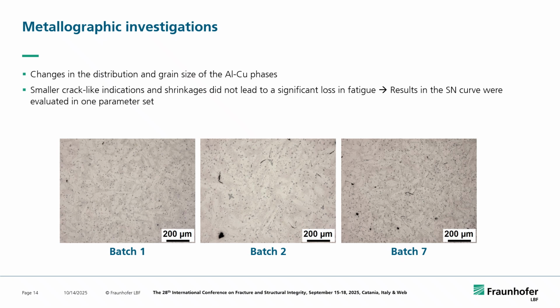We also did some metallographic investigation. They are not finished yet. We need to take a closer look at this. What we could see between the different batches that we removed from the 50 millimeter casting design is that we have sometimes changes in the alu-copper phases and the grain size. And we have some smaller crack-like indications on batch 2 and sometimes also batch 7, but they did not really lead to a significant loss in the fatigue strength, which was good and showed that even smaller signs and indications will definitely not influence the fatigue strength and the integrity of the complete product.